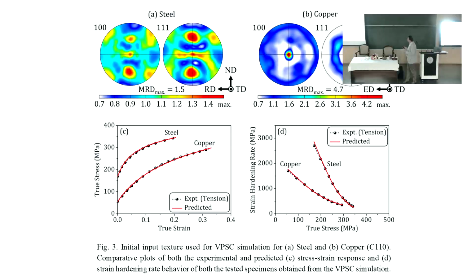So this is taken into account in the simulation. You discretize the initial texture into your grain orientation distribution used for the simulation, and then introduce it, and it's taken into account in this way. That's why it's added. If it is not done, we cannot get such a good agreement. It's also important to take into account the initial state of the material as precisely as possible, which must include the orientation distribution. Again, here the strain hardening rates and the curves themselves are very, very satisfactory.